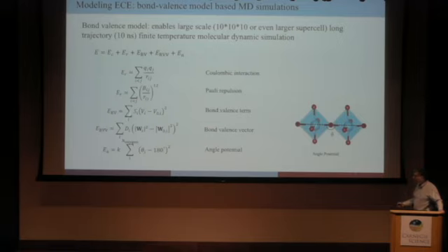But the idea is that if an atom's getting its bond valence by summing up the bonds of its neighbors, maybe it likes that all those bonds have a vector sum of 0, or maybe it likes that it has some asymmetry to its local environment, and that can be input with this term. And then finally, we had a small angle potential that if some of the octahedra in the model without this term have too large or too small octahedral rotations, there's a fine-tuning that can be done with a single parameter here of how much the octahedra like to rotate.